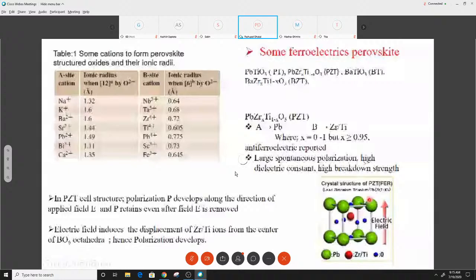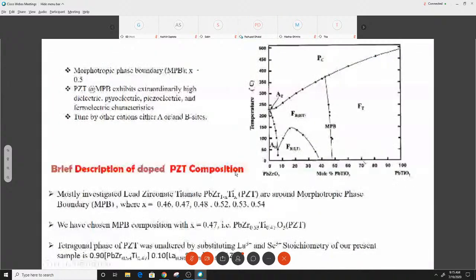This is a morphotropic phase diagram of the PZT compound. The higher the titanium, it shows the tetragonal structure, and the lower the titanium, it shows the rhombohedral structure. When x is equal to 0.5, this is said to be the morphotropic phase boundary. We have chosen x equal to 0.47, and we stabilize the tetragonal phase by substituting lanthanum, with this stoichiometric formula.